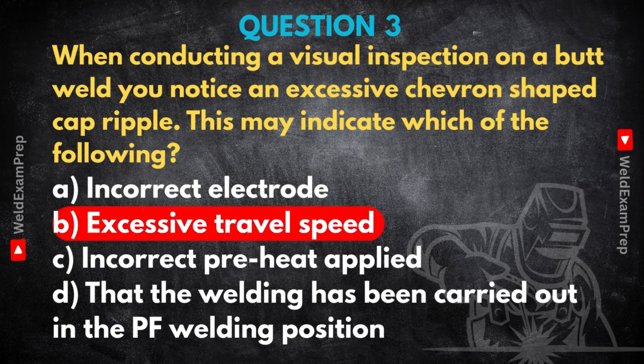Okay, excessive speed. What does that look like exactly? Chevrons, like V-shapes. Yeah, imagine V-shapes pointing back towards the start of the weld, but they're really elongated, pointed, and spaced quite far apart. Not the nice, rounded, evenly spaced ripples you want to see. It looks rushed. Like skid marks, almost. Kind of, yeah. It happens because the welder is moving the arc too quickly for the amount of heat being put in. The molten weld pool doesn't get enough time to flow out, settle down, and solidify smoothly. It freezes too fast in that pointed shape. Exactly. The arc moves on before the puddle can properly form and flatten.